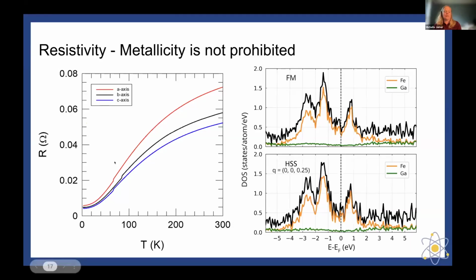And what's interesting is when you take a look at the resistivity or the resistance graph in this case, you can see right where the transition from ferromagnetic to the helical spin spiral occurs by looking at this little discontinuity around 70 Kelvin or so. And you'll see that the transition is slightly different between the A, B, and C axis due to the differences in how the magnetization is ordered.